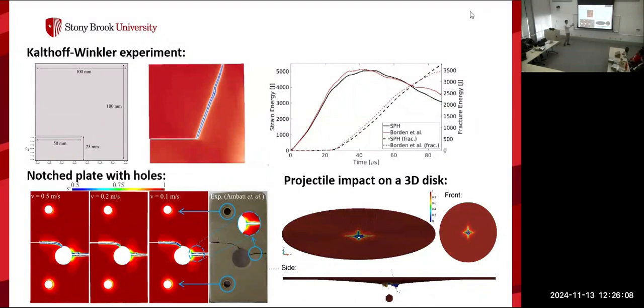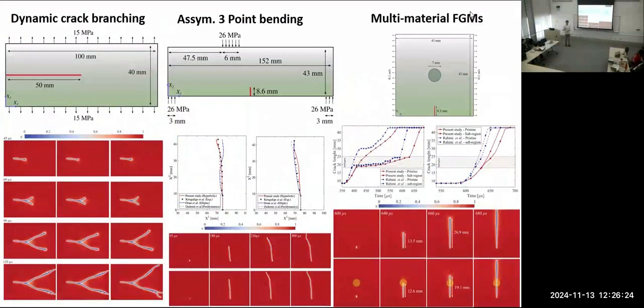So far we have a fracture model that can handle the fracture in simple isotropic linear elastic materials, but we are still unsure if it can handle scenarios with very extreme conditions. To test that, we applied it to a different material, which is called functionally graded materials. Functionally graded materials are an advanced type of composite materials that are usually used in aerospace and marine engineering. They have very convenient material properties. We tested our method on those, and as you see, the results are in good agreement with what people in literature have seen.